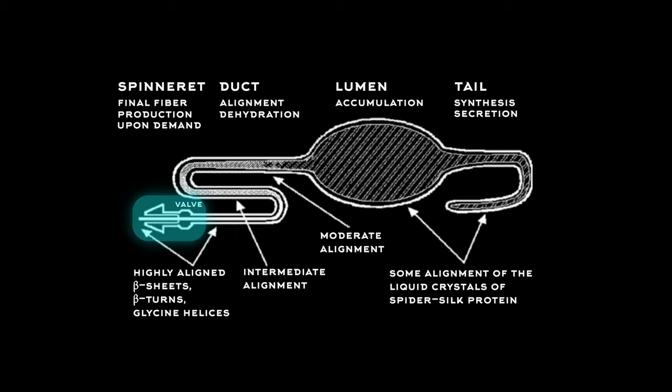It has been shown that when in solution, unfolded polyalanine chains tend to form polyproline helices. The protein prior to fiber formation could be in proline helix form. This may be the method through which the fibers do not form until the dope passes through the duct, where the polyalanine chains and the GPGXX regions begin to form highly aligned beta sheets and beta spirals, respectively.